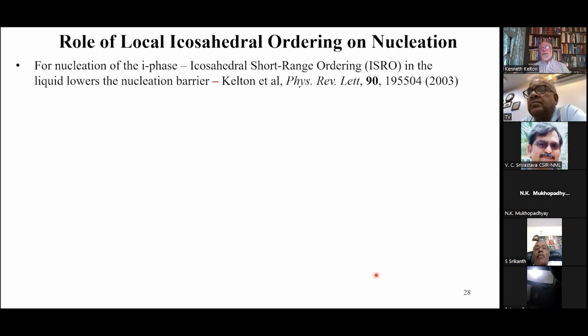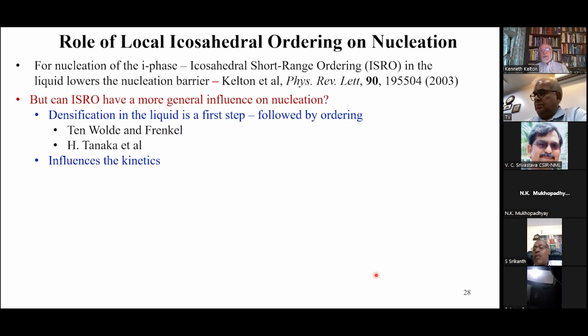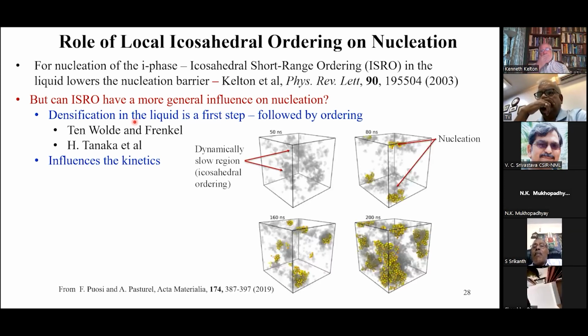So what's the role of icosahedral ordering in the liquid? Well, my understanding is that the structural ordering of the liquid is catalyzing the nucleation. But you could argue that it can have a more general influence on nucleation, where it actually helps other phases in addition to the quasicrystal. And that's been argued by Ten Wolde, Frenkel and Tanaka, where they argue that nucleation is a two-step process: first, densification of the liquid, followed by ordering of that region of the liquid. And that could also be supported by changes in the kinetics.